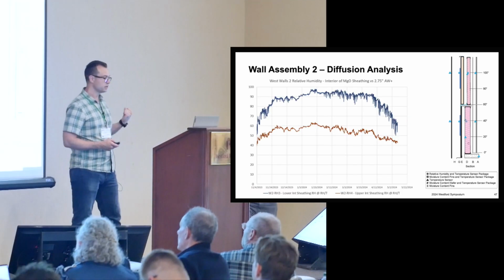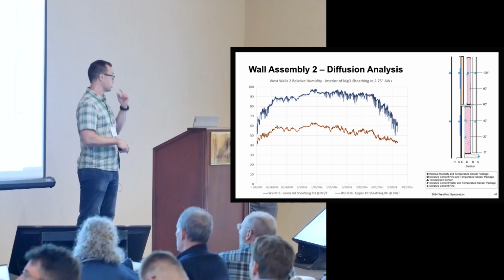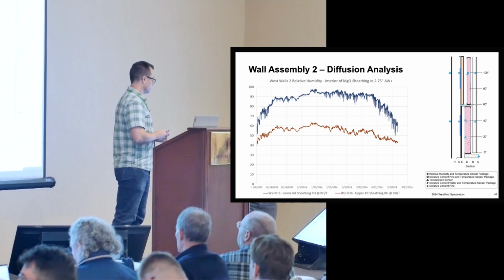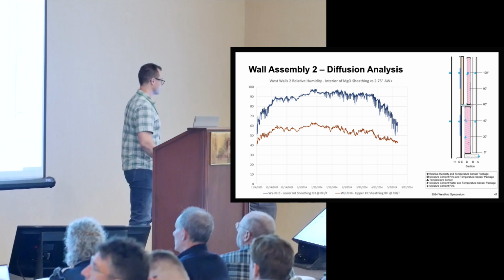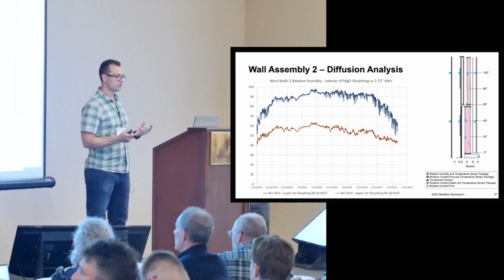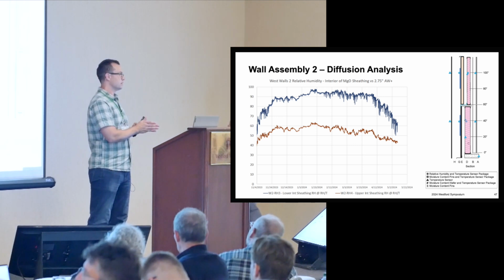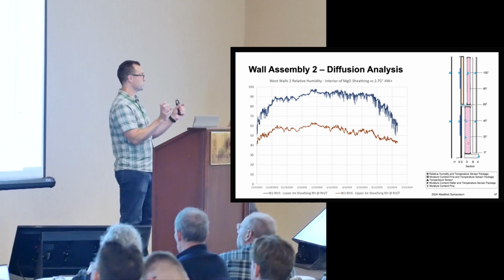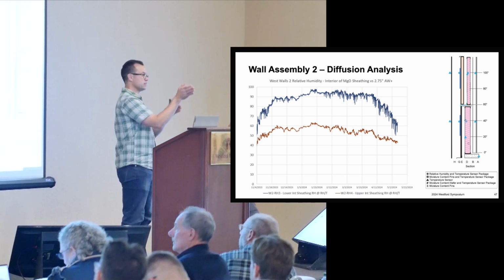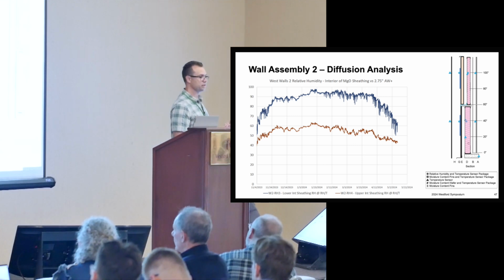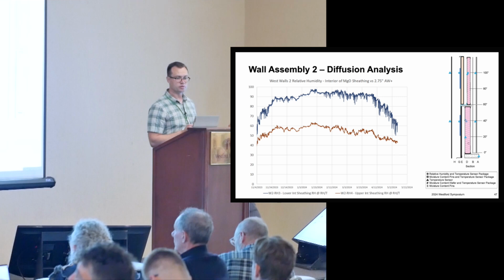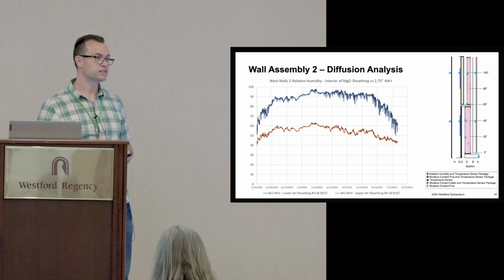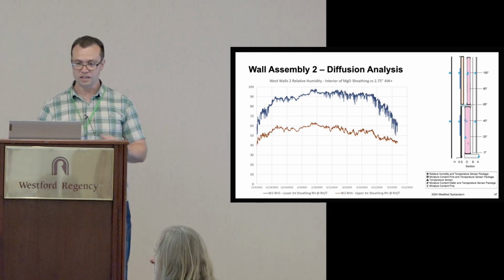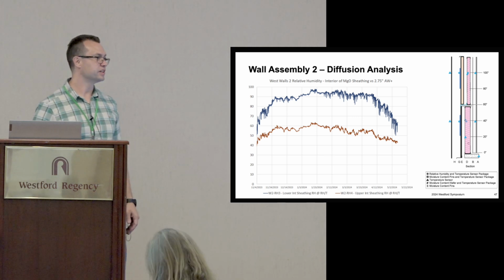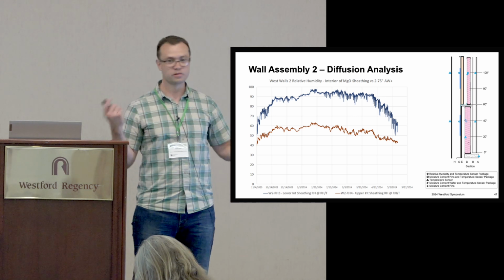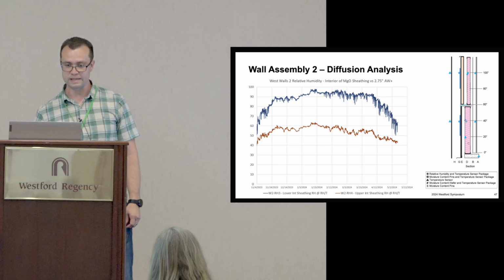So early season takeaways, that is November to May, and this is the stucco wall. No, this one I was looking at, sorry, this is wall 2. The stucco wall's next. What I wanted to see on this one was the MgO that's bare on the lower 2x6 versus the 2x4 with Armor Wall Plus that has insulation on the back of it. What's the relative humidity at the inside surface of that, which would be the worst case scenario for air leakage condensation to the back of it. So I wanted to see what our humidity baseline is now versus when we start injecting air. So that's the difference with and without exterior insulation. I know it gets harped on at this conference a fair bit. Exterior insulation works, and there's just a quick snapshot of some of that.